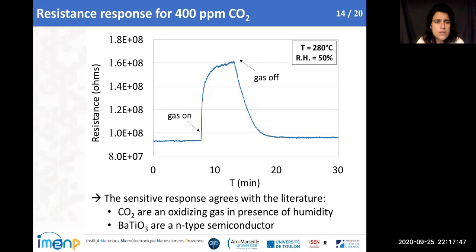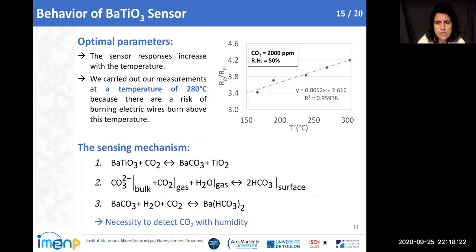If you look at the resistance response we obtain for 400 ppm of carbon dioxide, here we have an increase of the resistance when we put the gas on, and when we switch off, we return to the baseline. So we don't poison our surface. And also we can say that, like in the literature, we have an oxidizing gas and an N-type semiconductor. This work has been done at 280 degrees and 50% of humidity, which is the value used by the manufacturers in industry when they make the tests.